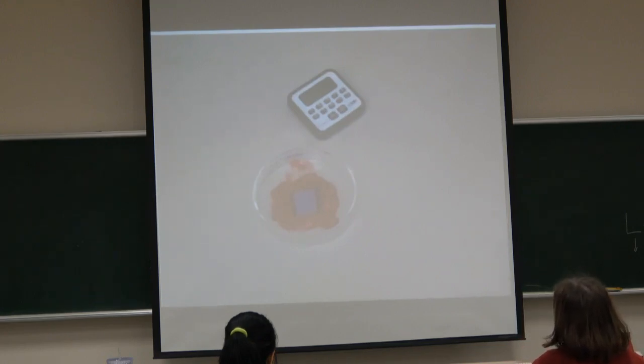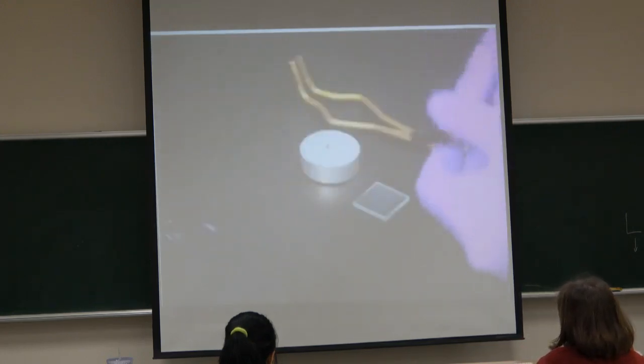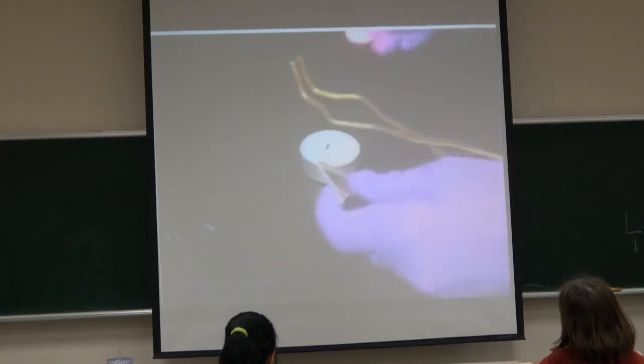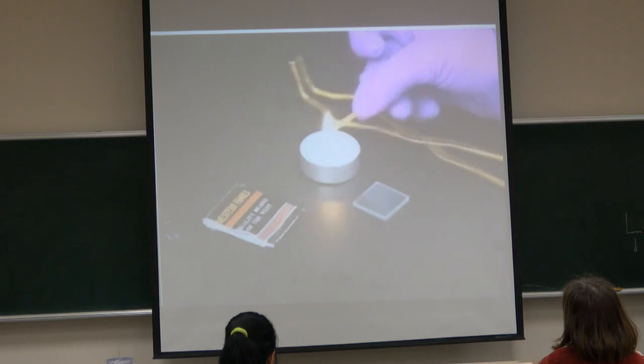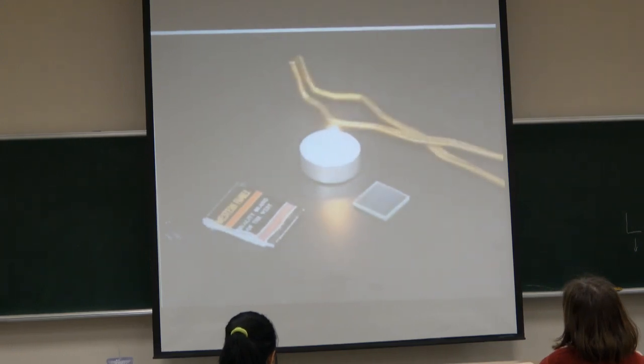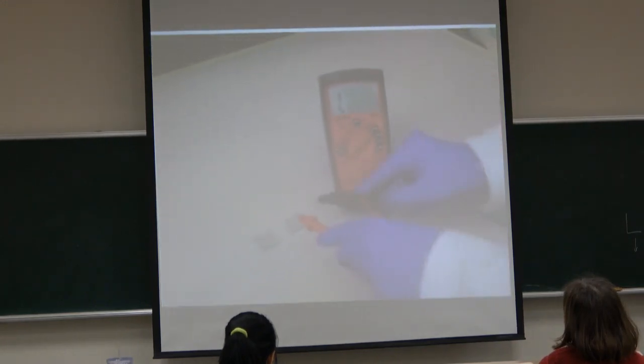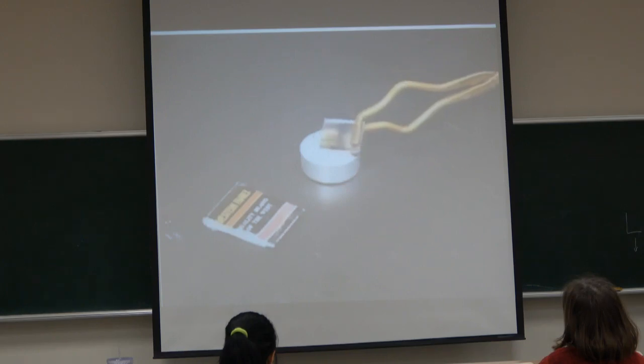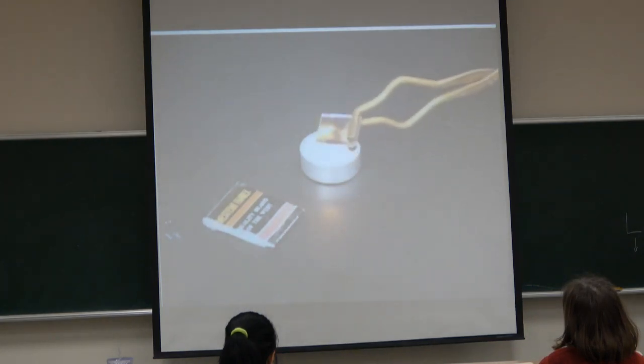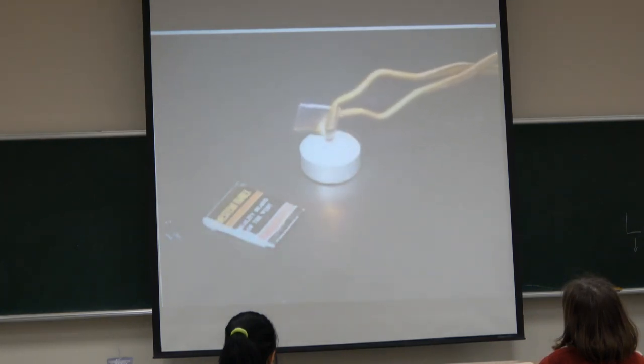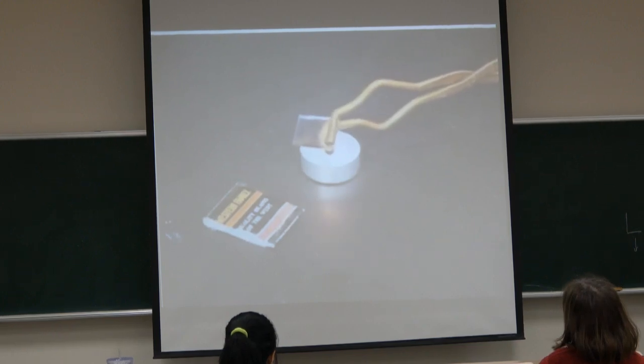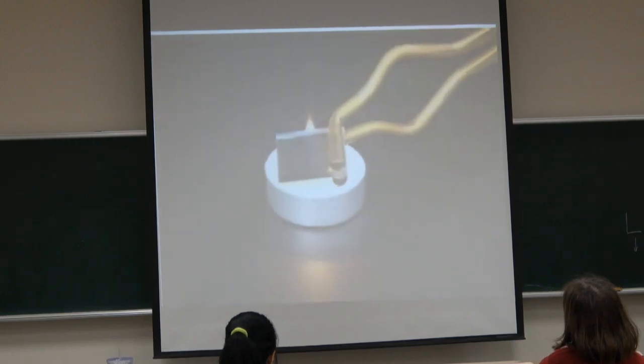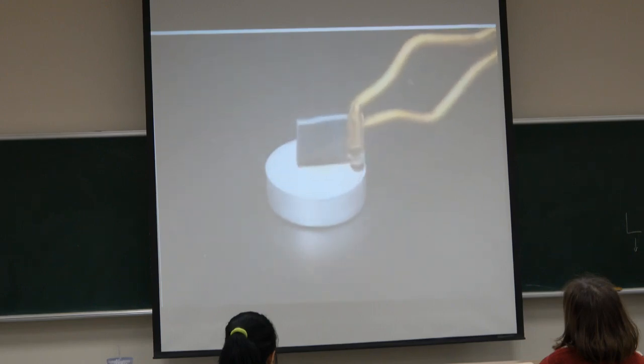Titanium dioxide electrode is being stained in the berry juice. Make the counter electrode from another piece of conductive glass. Step 2. Light a tea candle with a match. Step 3. Determine which side of the clean glass plate is conductive with a multimeter set to resistance, ohms. Hold the slide by one edge with the metal tongs. Pass the conductive side through the middle of the flame until the entire side is coated evenly with soot, except for where the metal tongs were.